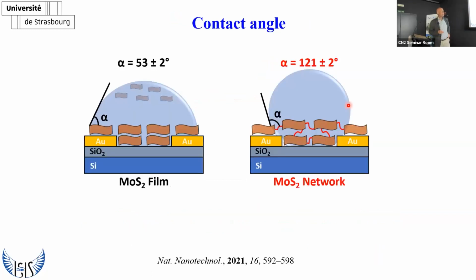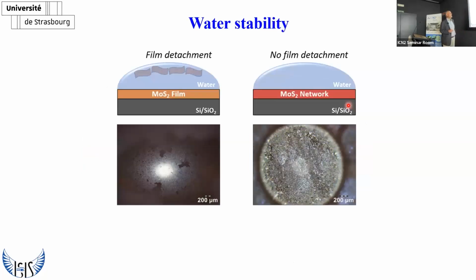the basal plane. Now, upon network formation, the film became a network that exhibits a much higher hydrophobicity compared to the film, which allows us to have, let's say, networks that are stable in water, don't detach from water, whereas the film was detaching once it was exposed to water. Therefore, of course, for water-based applications, the network is more interesting.